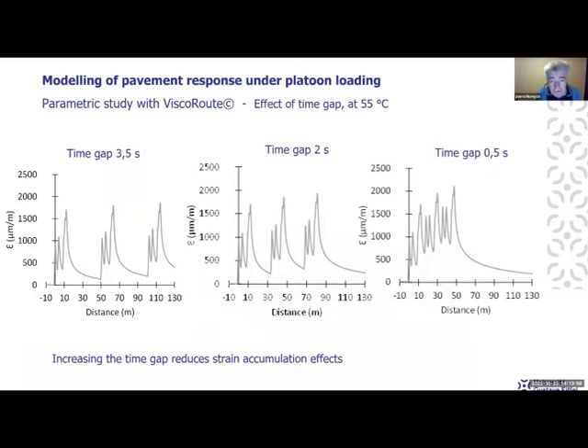We also studied the effect of the time gap between the trucks. So here you have simulations of transverse strains with 3 time gaps, 0.5 seconds, 2 seconds, and 3.5 seconds. And you can see that with the short time gap, you have a strong strain accumulation. And with the time gap of 3.5 seconds, which is relatively high, maybe higher than what you would apply in a platoon, you get practically no strain accumulation and a similar behavior to single trucks.